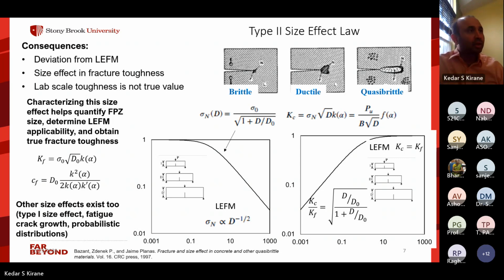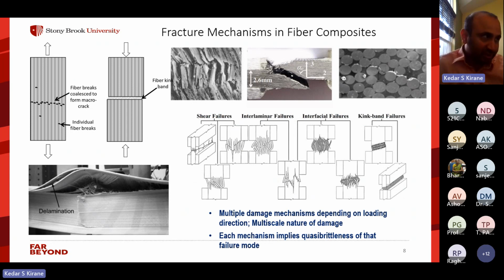structural scales. Now, coming back to the composites, they are, like I said, very, very heterogeneous, and because of their arrangement, like how the fibers are, they have a large variety of failure modes, which depend on the direction of the load applied. So for example, if you have a single layer or lamina subjected to tension, it is a tensile failure, and it occurs by a lot of these fiber breaks, as shown here. On the other hand, if it is a compressive load, the failure mechanism is completely different, and it occurs by a formation of a fiber kink band, which I will elaborate on the next slide.